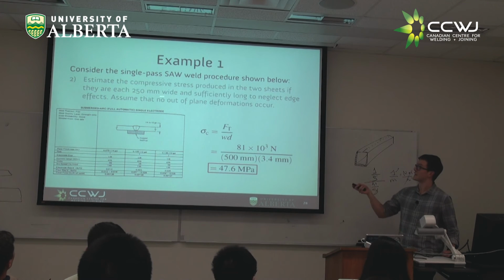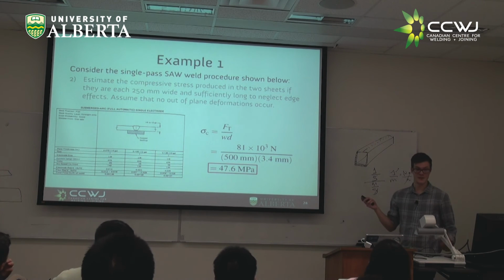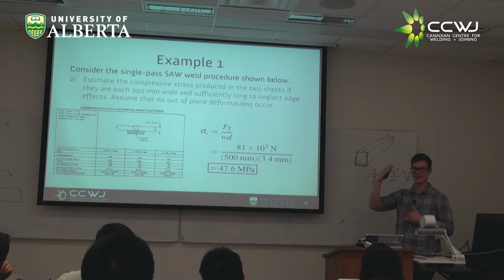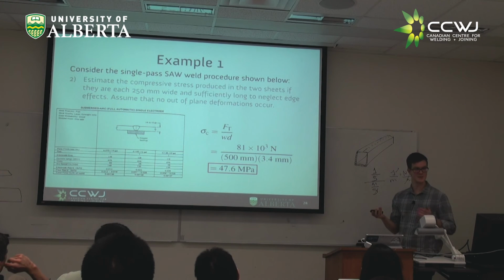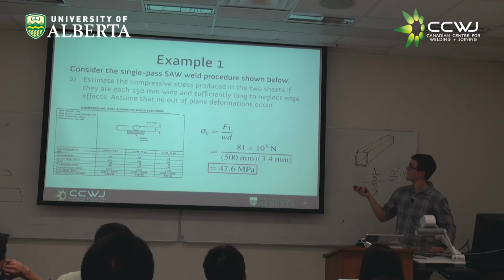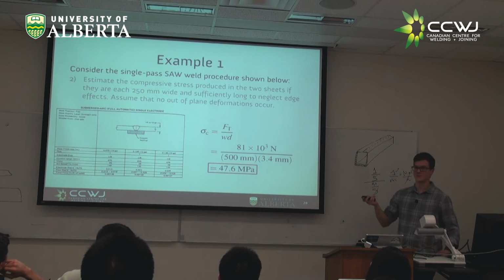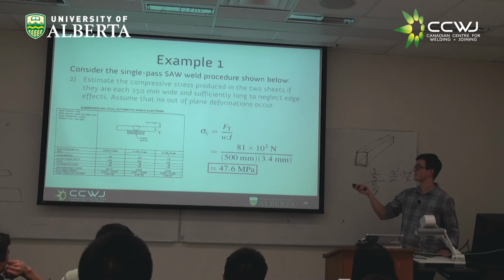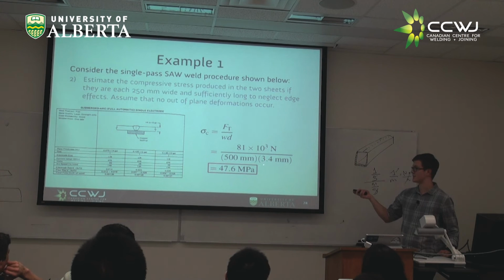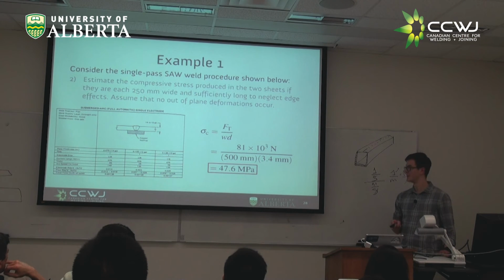Now, what if we give some thickness to those plates, or some width? If we say each of those plates are 250 millimeters wide, and we're going to neglect out-of-plane deformations, which essentially means this heat is distributed evenly through the thickness, which for a thin plate is a pretty reasonable assumption. Let's calculate the compressive stress. This is even easier. We take our tendon force, we divide by the total width and the thickness. Thickness, 3.4 millimeters, that's 0.135 inches. Total width, 250 on each side, is 500 millimeters. 47.6 megapascals.